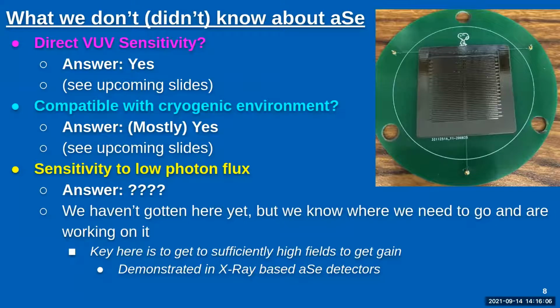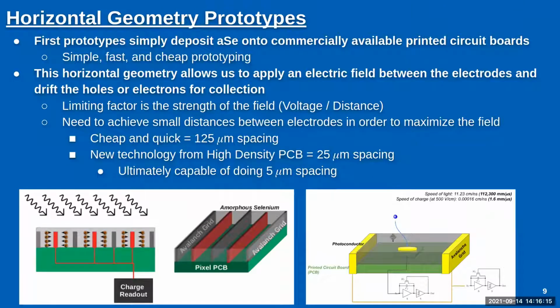I'm showing you here a picture of one of the first prototypes, which we produced, with selenium lovingly put on a board that we call the Snoopy board. We chose initially to think about the prototyping in a horizontal geometry. This is because it's relatively easy to deposit selenium as an amorphous substrate onto commercially available printed circuit boards, to allow us to do simple, fast, and cheap prototyping. The horizontal geometry also allows us to apply an electric field between these electrodes to drift holes and electrons for collection, where the limiting factor is the strength of the field that we can achieve. You can do this one of two ways: you either turn the voltage up or you decrease the distance.